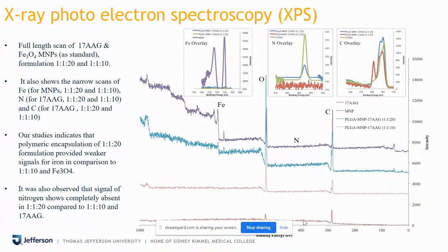And the red line, which is at the bottom, is about the polymer, the drug, the standard drug. Now, if you see this whole scan spectra, it's very difficult to see a 400 peak over here, which I am just pointing the cursor to. It's extremely tiny. These instruments are extremely sensitive, and sometimes it's very difficult to measure the nitrogen signals from a molecule of a drug, because you need to think that right now you're thinking about a drug in terms of a single structure which consists of 1 or 2 nitrogen atoms. So from that perception, you have at 400 a tiny bump.